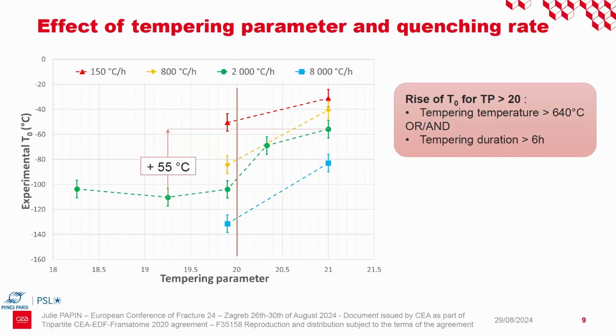Now, if we represent the reference temperature as a function of the tempering parameter, for each quenching rate we can observe a plateau of T0 under 20, and then a rise of T0 for a tempering parameter over 20. And this tempering parameter of 20 corresponds to a tempering temperature over 640 degrees or a tempering duration over 6 hours. And the two conditions can be combined.